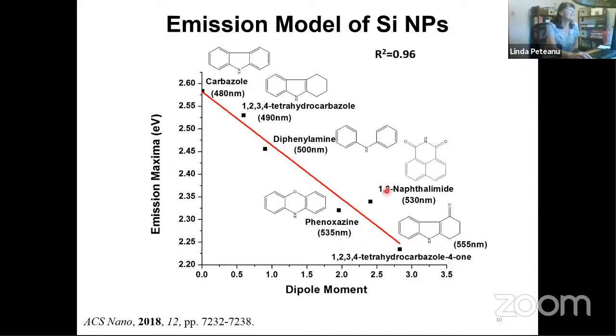So it suggests that there is a charge transfer component to the strong emission that we're seeing, and that can be relatively well predicted in a simple way from the ground state dipole moment of these molecules. So that again has already been published.